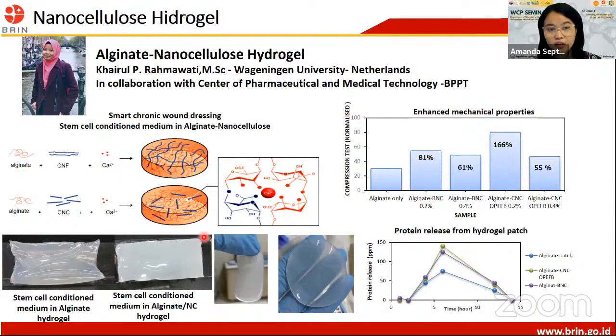She successfully developed a smart wound dressing by introducing bacterial nanocellulose into alginate-based hydrogels. As you can see from these figures, when we haven't yet introduced the nanocellulose into the alginate system, the morphology of the alginate still shrinks and cannot maintain good stability after the solid hydrogel forms. Once we introduce our nanocellulose, interestingly, it can give a good shape integrity to our alginate. And in the mechanical tests, we can see that the nanocellulose inside the hydrogel significantly enhances the compression test properties. And for protein release, our nanocellulose can give more protein release in the hydrogel patch.